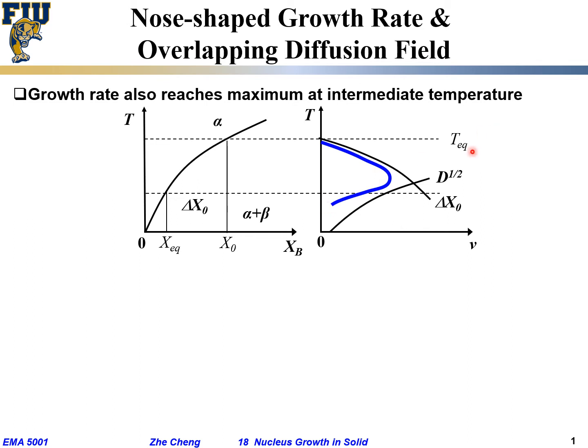Remember, Teq is our equilibrium temperature. We have two terms together determining the growth rate. One is driven by D to the power of half. What is that? Diffusion coefficient. Naturally, the higher the temperature, the higher the diffusion coefficient. Even though it is square root, it's still the higher the temperature, the higher this term.